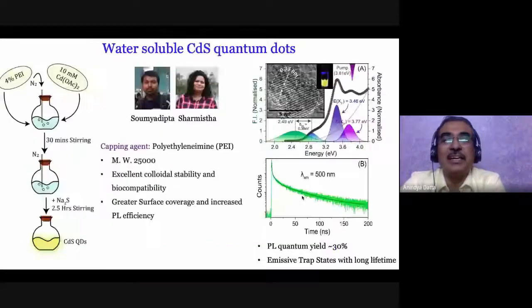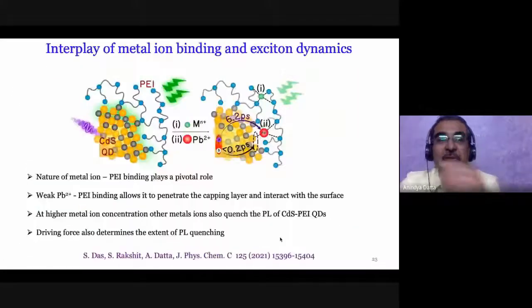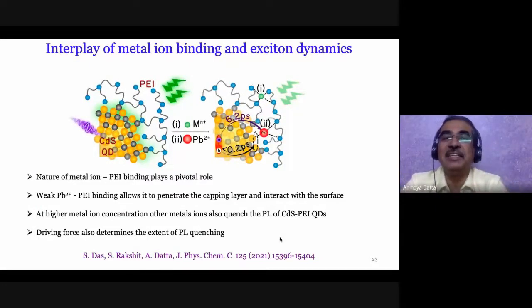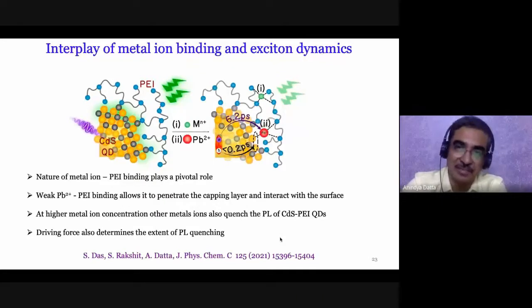One thing I forgot to say is that they use a different capping agent. The capping agent they use is polyethylene imine, a polymer. And it turned out that it is the polymer that gives the specificity of this cadmium sulfide nanoparticle towards lead. Now, PEI can actually bind most of the metal ions, so the metal ions don't reach the surface of the quantum dot. In order to quench the photoluminescence, they must reach the surface. Lead does not like to interact with PEI.